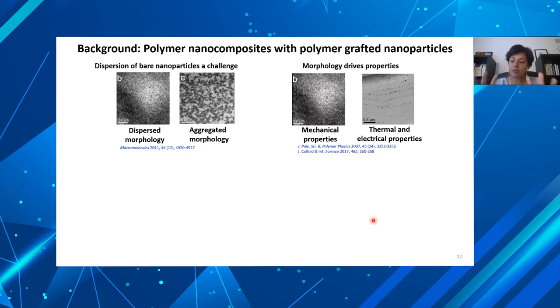So in this field of polymer composites, people are trying to control where the nanoscale fillers, nanoparticles, go within the polymer matrix. And if you had just bare particles, getting the particles to disperse in the matrix is often a challenge. And we know you have to achieve these different morphologies for different properties, right? If you want certain types of conducting properties, you need a certain morphology, mechanical properties, a certain morphology. So controlling where the particle goes and the morphology of the composite is important.